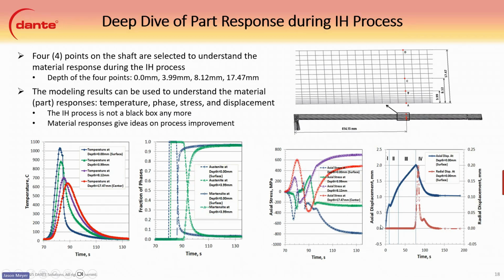And lastly, we have the axial displacement. We can see the part length change here in that section. We can see, basically, heating up through thermal expansion here, and then cooling back down, and the radial dimension here. And then we can see the same thing at the radial displacement, the bulge that we saw in the contour earlier, quickly spikes up here to about 0.2 millimeters and then comes back down. It has a little bit of a jump here from the martensite transformation, and then back down to regular levels here.